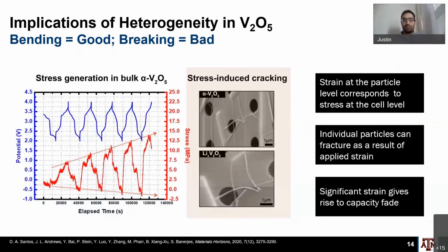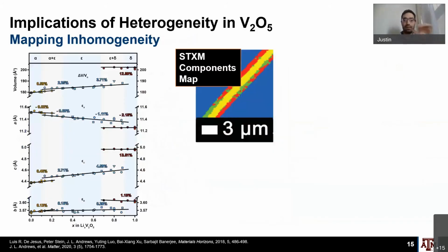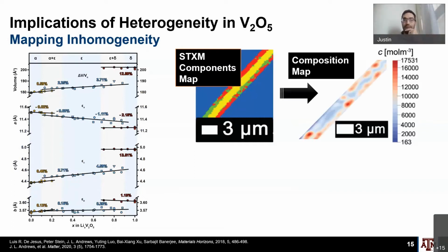And so the way that we've leveraged STXM in a unique way is that we can process these images through principal component analysis and actually map out the different spectral features that we see. We can assign different extents of lithiation, essentially compositions, to these spectral features to create higher resolution composition maps. What I'm showing now is an STXM image that was converted to a principal component analysis image. This is a statistically processed image, and then we can generate a composition map.